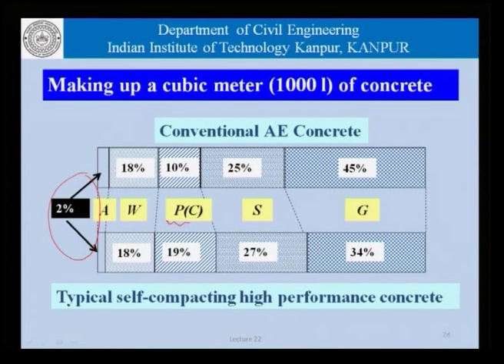As far as powder or cement or fines is concerned, there is a marked difference. That is about 10% in conventional concrete, whereas in self-compacting concrete it could be as high as about 18 to 20%. The sand is not really so much different, and this increase here is compensated by a corresponding decrease in the coarse aggregate percentage. So, in the end result, self-compacting concretes have a larger paste volume